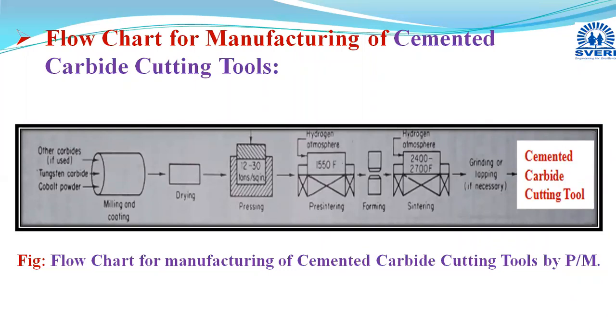Final sintering is done at 1350 to 1550 degrees Celsius in the reducing or hydrogen atmosphere or controlled environment. Here we are doing this final sintering for 2 hours, where cobalt melts and it cements or joins the carbide particles which are present in that powder mixture. Hence it is termed as the cementation method, and this carbide cutting tool is termed as cemented carbide cutting tool, because cementation is occurring due to melting of cobalt.